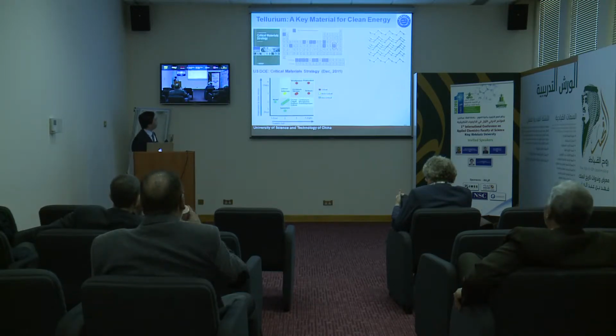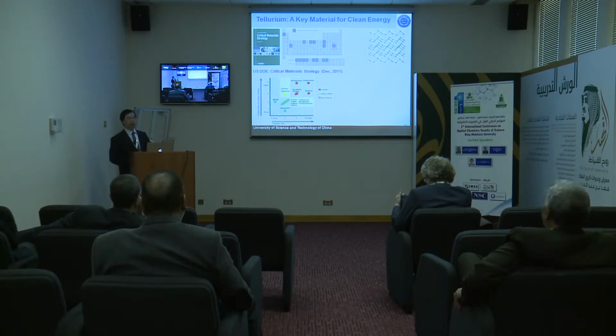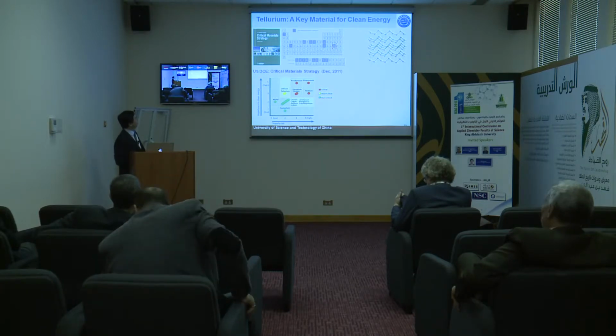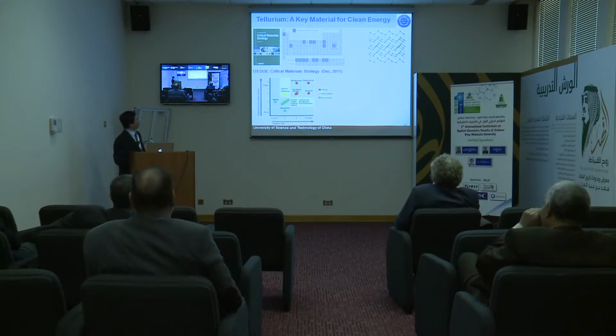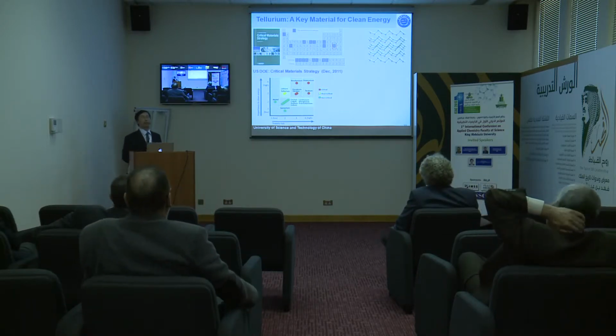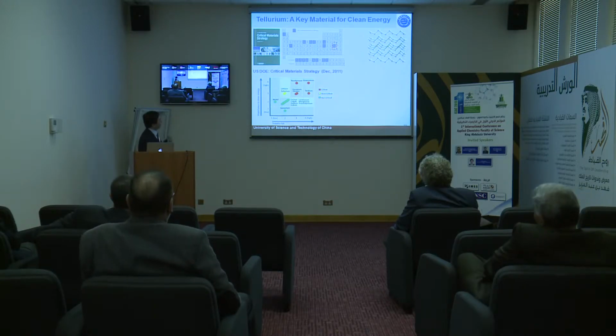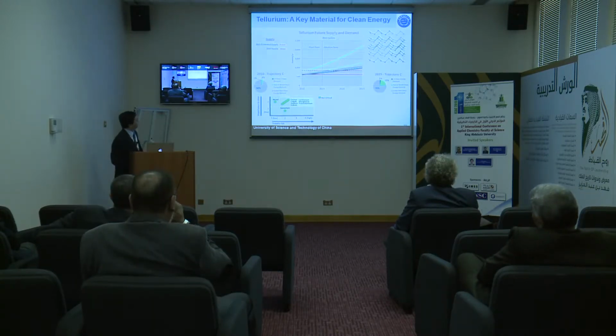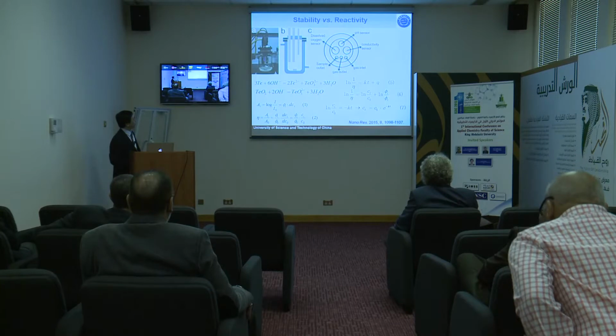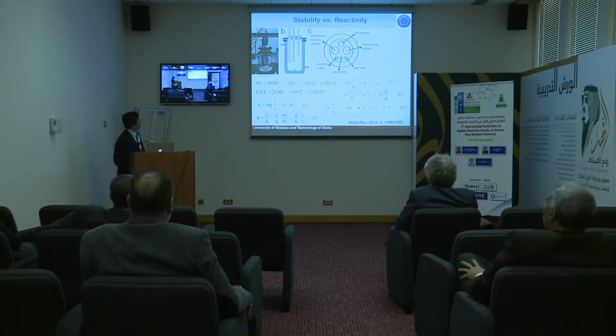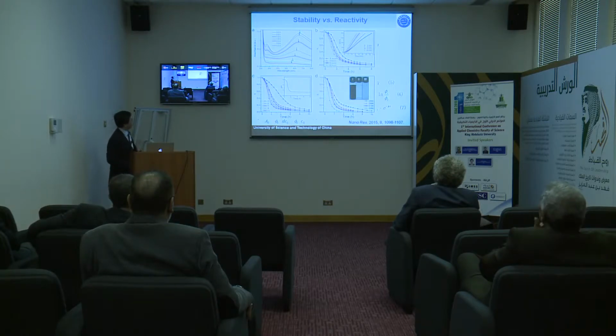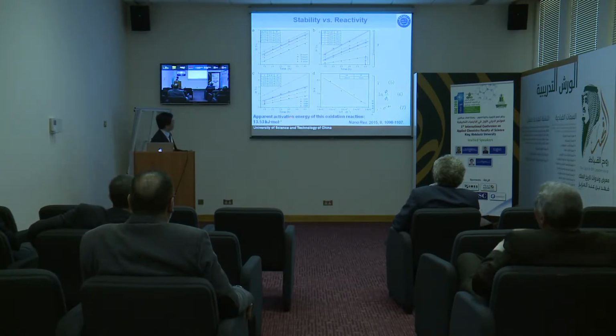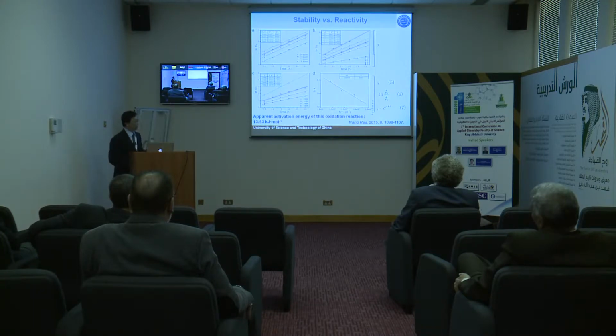We studied this because the element tellurium is a very key material for clean energy in the future. If you look at the DOE critical materials strategy, they list tellurium as one of the 16 key materials in the future, because this element is very, very important. So that's the reason why we chose this system. Then we studied the oxidation kinetics of these ultra-thin nanowires. We carefully studied this oxidation process. Then finally we can calculate the apparent activation energy for this oxidation reaction. You will see the activation energy is really very low.